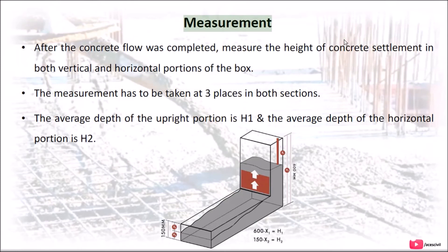Measurement: After the concrete flow was completed, measure the height of concrete settlement in both vertical and horizontal portions of the box. The measurement has to be taken at three places in both sections.